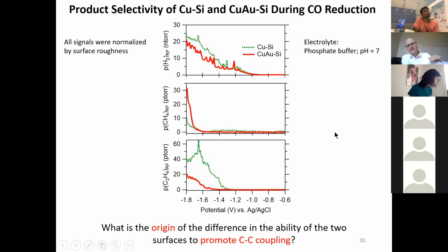And the reason for that is that it's reversibly bound to the electrode, unlike on platinum electrodes, where you can just purge all your CO in the electrolyte away, and then you do electrostripping and you just count electrons, and then you know how many CO molecules you had on your surface. Unfortunately for the copper system, you can't do that. And it's really a shortcoming, because I think the spectroscopy could be so much more insightful if we could really tell how much CO we actually have in terms of absolute coverage. But I think the answer to the question is we're well below the saturation coverage.